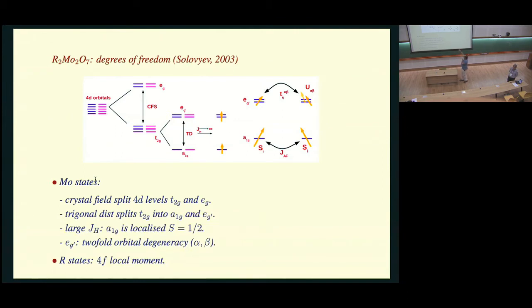So, in fact, I should have added another degree of freedom on this with a very weak coupling to this S, let us say. So, this is a molybdate local moment. This is not a rare earth local moment. The molybdate has S equal to half, which I cheated and used as a classical moment. But there is also an S equal to 5/2, 7/2 sitting on the rare earths. It just so happens that its coupling to the rest of the subsystem is not that strong, but it's important for many of the anomalous Hall chirality related issues. But in this story, they have just been completely ignored.